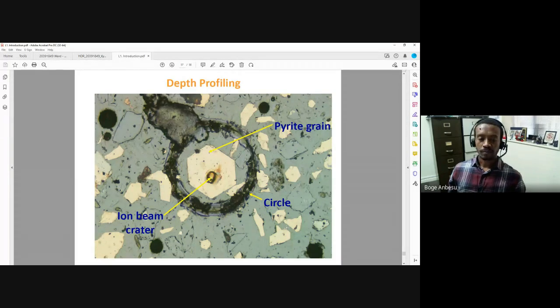So I say, now I did an elemental assay. There might be something relating to gold, or there might be something related to platinum in my sample. I can go detect even the tiniest amount of gold or platinum in the sample. In this case, the detection limit can be parts per million or even lower for something like secondary ion mass spectroscopy. Now I know quantity. Once I know quantity, I say, okay, let me look for those gold or platinum in the various minerals I have in my sample. Go to pyrite, let's see if the pyrite has anything. Go to the chalcopyrite, find if there's gold there. And platinum or whatever I'm interested in, I can go there and find out exactly where the gold is located.